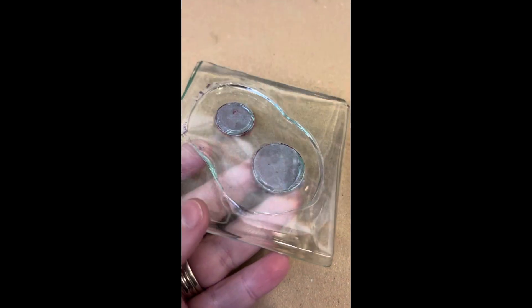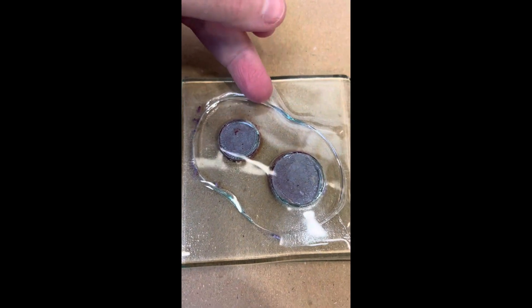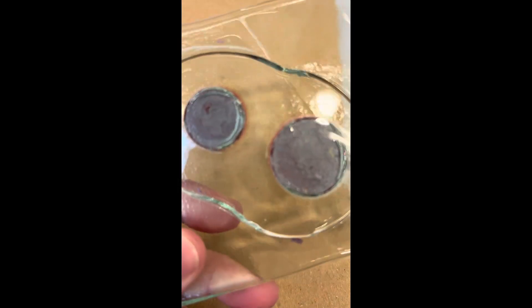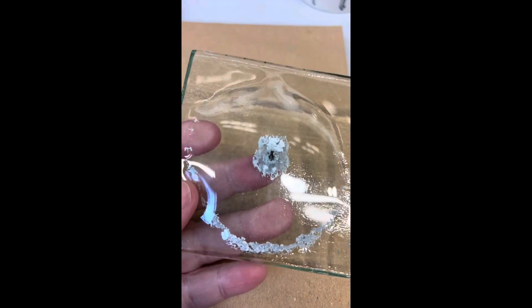This one is the copper coins, and I've got to be careful with this one — it has cracked to the point that you could actually probably smash it out. That's because the coins were a bit thick really for the glass. It's kept a nice colour on the back, but that bit looks quite dangerous.